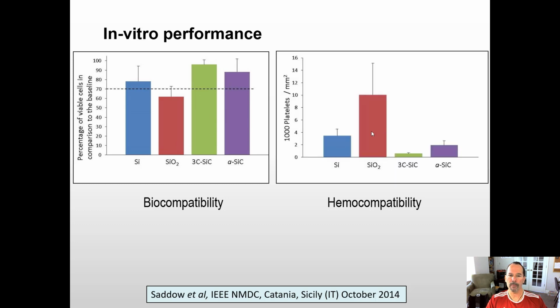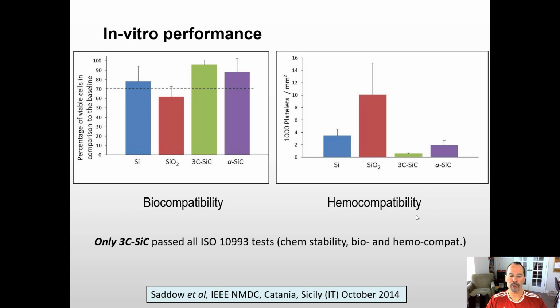Looking at hemocompatibility, where we're looking at platelet attachment and activation on the surface, we see again that oxide is just not a good material to be in contact with the blood. Cubic silicon carbide is excellent, and amorphous is quite good as well. So in the test that we did, this was a DARPA program that we had, we looked at about 7 different materials. I'm not at liberty to disclose what and from whom, but of all the material systems we looked at, only one, cubic silicon carbide, passed all of the tests. And by the way, this ISO 10993 standard is what must be satisfied before going to clinical trial. So it's very important. Both chemical stability as well as bio and hemocompatibility. Only cubic silicon carbide passed the test.